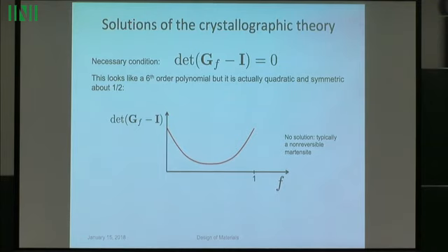And you can plot this for various phase transformations. Everything is measured at this level. It's just lattice parameters, really, symmetries and lattice parameters. And if you take a typical steel, some of the steels actually have roots, so they would satisfy this, but other ones do not, and those would all be non-reversible martensites.